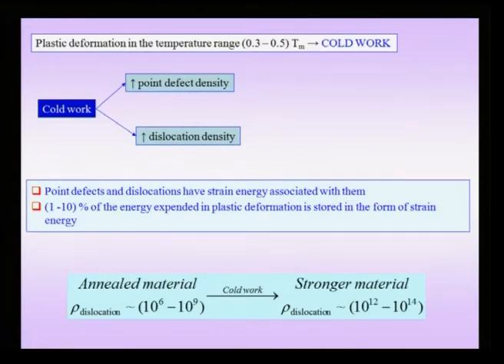Suppose we plastically deform a material, and we typically call this, when you do it under cold conditions, cold work. Under such circumstances, typically the point defect density, typically vacancies etc., increases, and also the dislocation density increases. At the end of these slides, we will try to understand the correct definition of cold work. For now we will assume that it is a low temperature regime, less than about 0.3 Tm, and we are doing working which is called cold working, and in the process we are increasing the defect density, which includes the point defect density and the dislocation density.